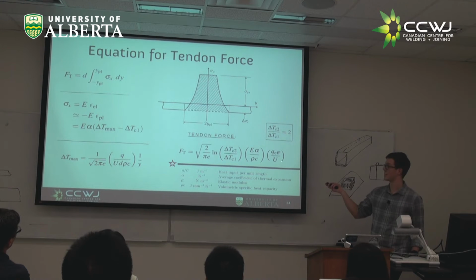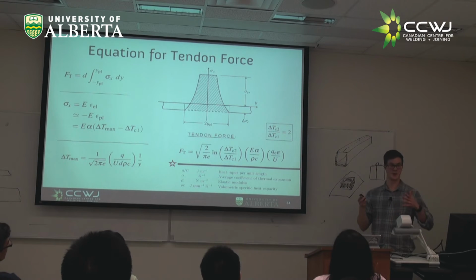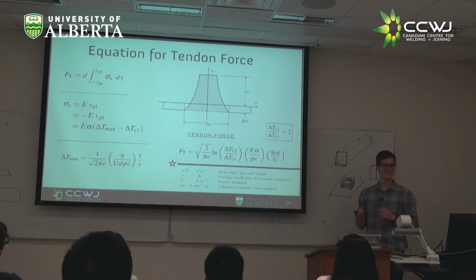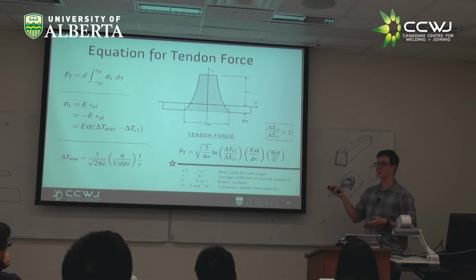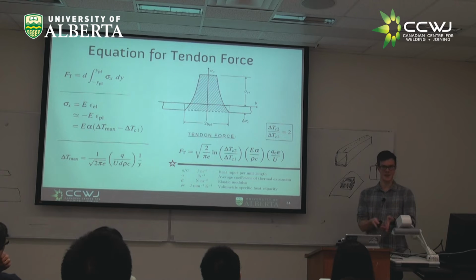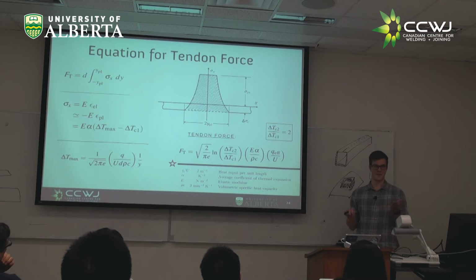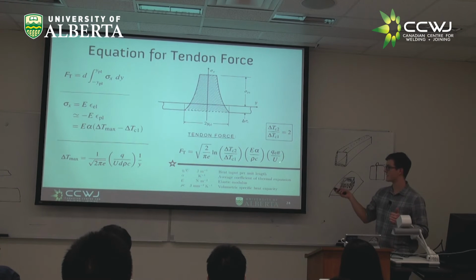So we have our heat input. In this case, we've written it explicitly as the effective heat input, because you can imagine if we start to deal with a practical problem of welding, which we want to get to, it's not going to be the total heat input that matters. It matters how much is actually getting into that plate. So this effective heat input, we're including whatever our thermal efficiency is. Because any heat that doesn't make it into the plate, we're not going to worry about from a stress perspective. From an efficiency perspective of welding, from how much power your machine's using, maybe it's important, but from a thermal strain perspective, if the heat doesn't make it into the plate, we're not going to worry about it. So we just care about the effective heat. And then this rho C is our volumetric specific heat capacity.